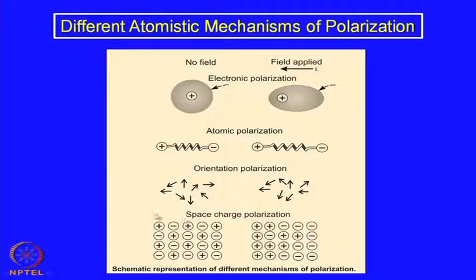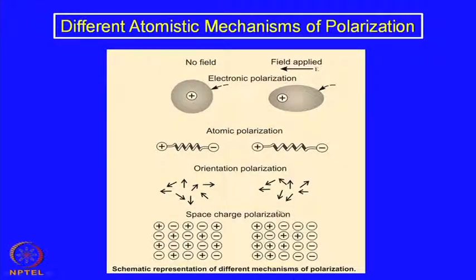So instead of a complete random distribution, you have a preferred distribution. On one side the positive charges move in one direction and the negative charge moves in the other direction and they get accumulated on the surface or the interface. And that also gives rise to an increase in dipole moment and therefore a polarization. Okay. So this is the last kind of polarization mechanism. So you have four different kinds of mechanisms by which the material can get polarized, or creation of dipole moments or increase in dipole moment. That is what can happen.